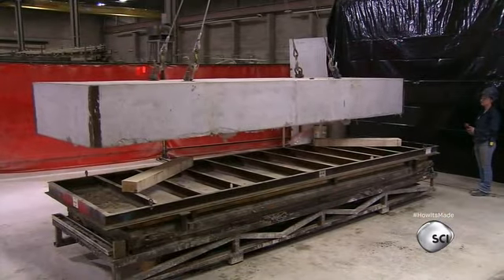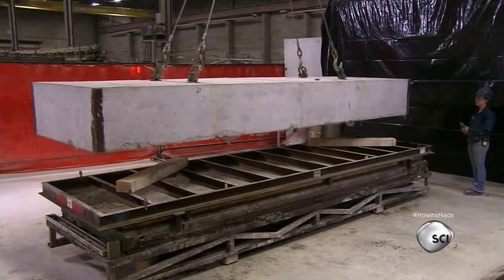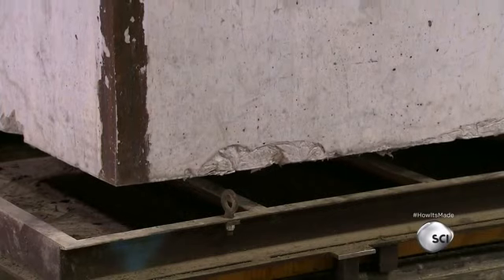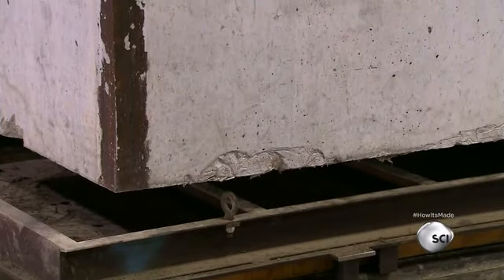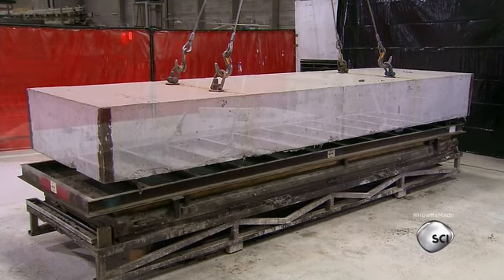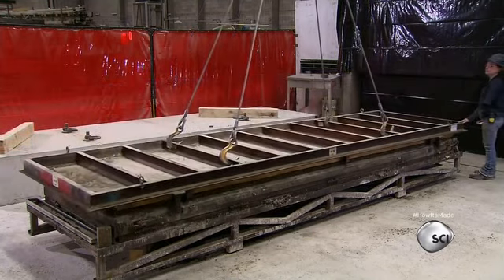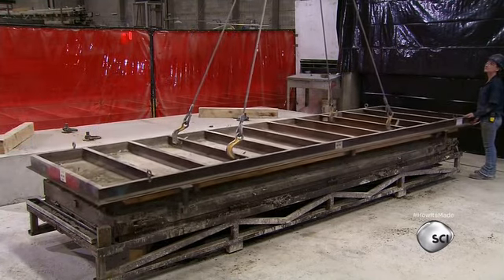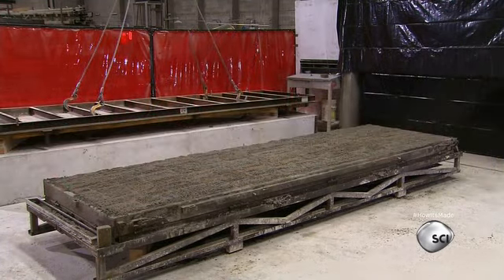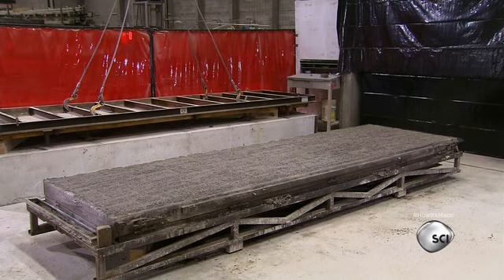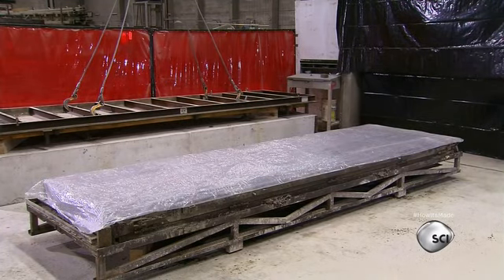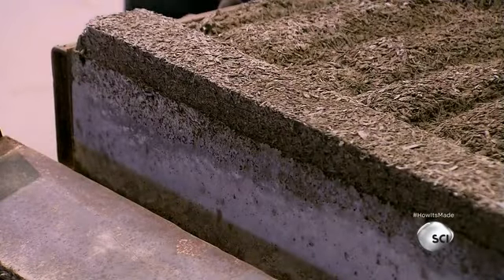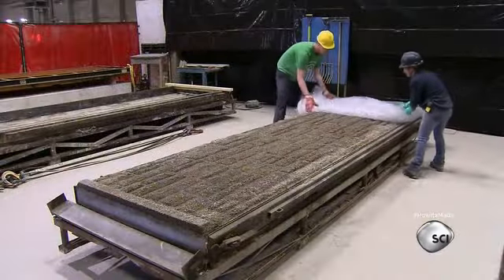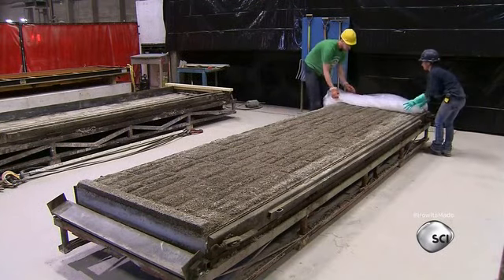They set a 10-ton concrete block on the mold, and pressure forces the mold patterns onto both sides of the casting. After a few minutes, they remove the lid and the imprint is revealed. They quickly cover the panel surface with a plastic sheet to prevent any evaporation of moisture as the cure continues. If the blend cures too quickly, it could crack.